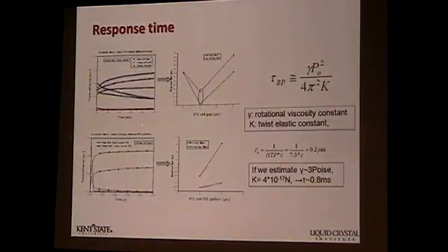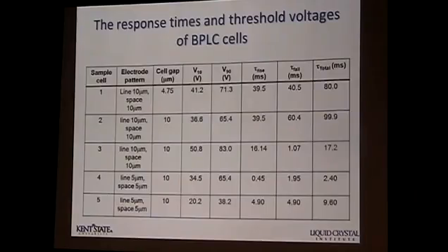And response time wise, I think in general, if you do some calculation with the materials' pitch, and roughly the viscosity of the materials, if you estimate that, and then you can estimate the elastic constants, and so the response time is roughly around 0.8 milliseconds for this type of materials. So eventually you can do some estimation from here.